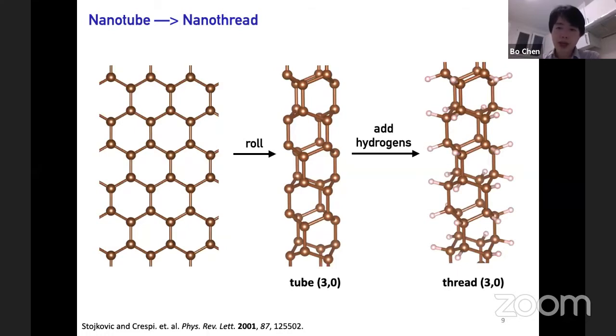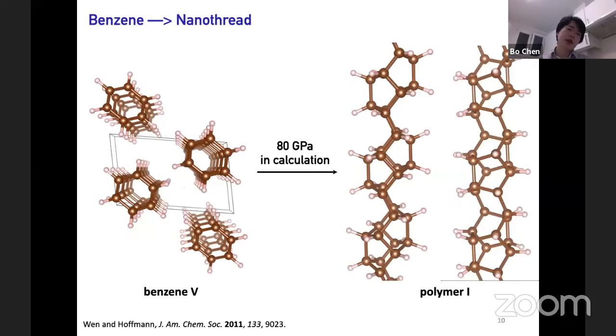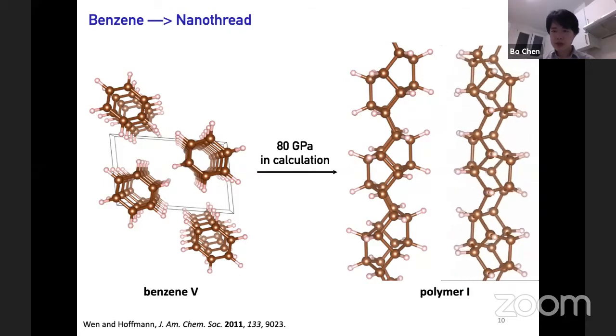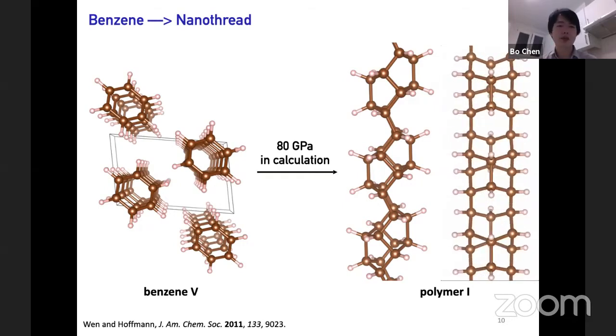And if you are an organic chemist, you can discern the different conformations of the six-membered ring, for example, the chair form and the boat form on the side. The second prediction is from the Hoffmann group, where they were studying theoretically the benzene V, which is a hypothetical phase under pressure. And they found that this structure spontaneously collapsed into a one-dimensional polymer, which they call polymer I. You can take a look at the structure here. So this work kind of hinted at nanothread synthesis from benzene under pressure.